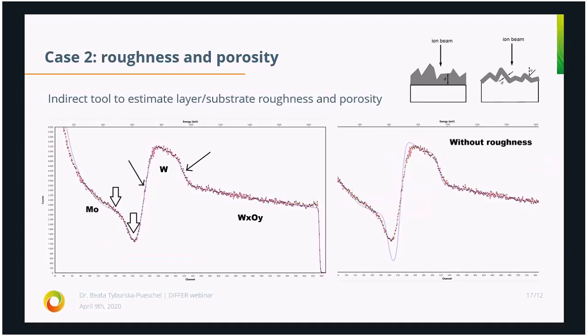Here on your right side, you have a spectrum. The red data is the measured data, and the blue line is the fitting, the simulation. And if I don't simulate any roughness, then you can see that the simulation doesn't fit the experiment. And if I simulate with the roughness, I can perfectly fit my data. And generally, the elements of the spectrum which tell me that there must be some roughness are the incline of this slope, incline of that slope, then the fitting of the molybdenum substrate, and definitely this dip is also telling me that there must be some roughness in in my samples.